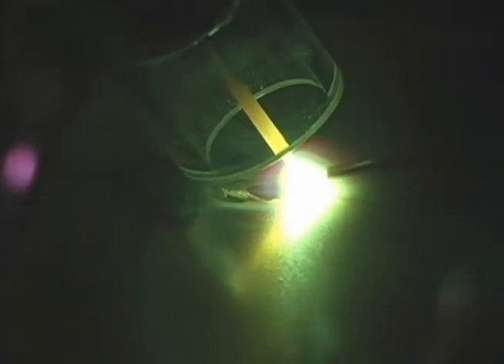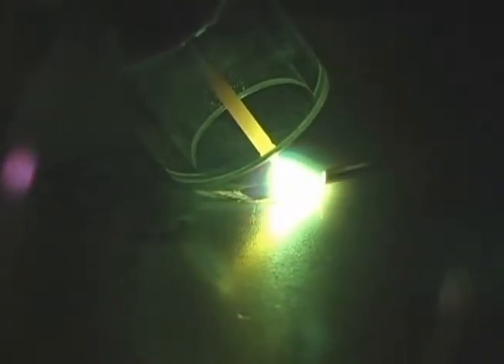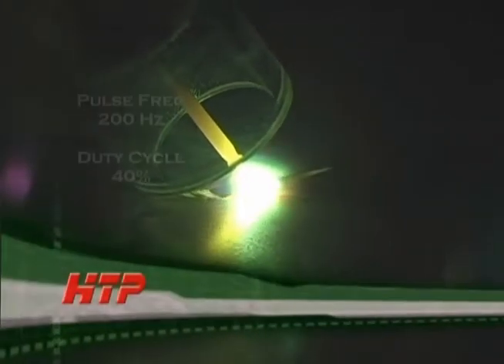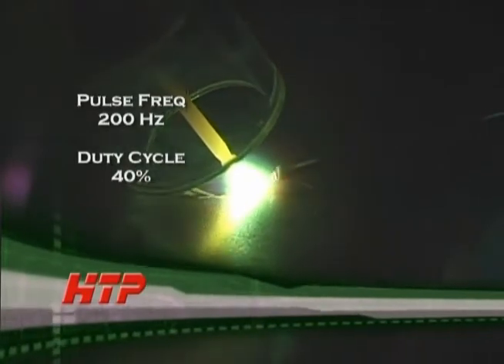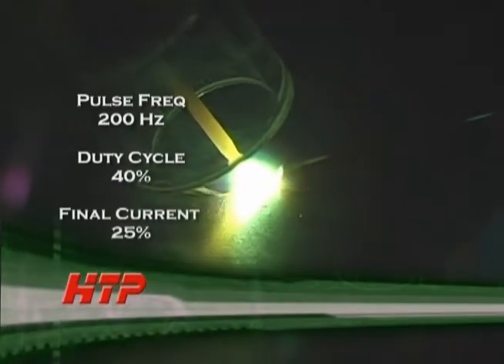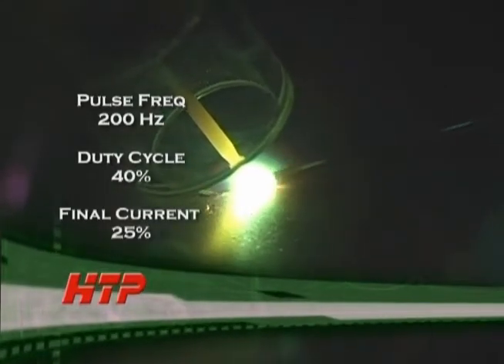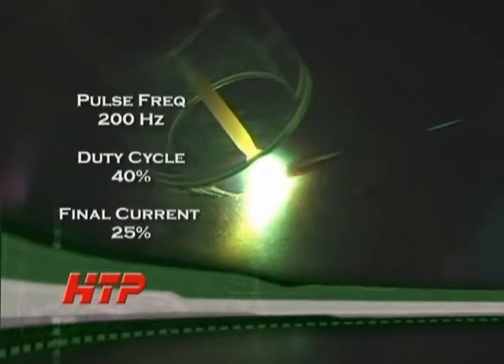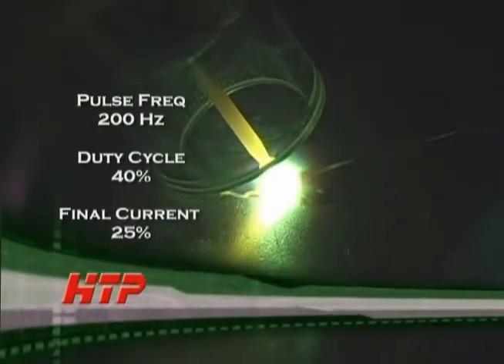In the second pulse example, we have raised the pulse frequency to 200 Hz or 200 pulses per second. You can only hear the machine pulse, not see the actual pulses since they happen so fast. The duty cycle is 40% and the final current is 25%. This really increases our travel speed, minimizes heat input while assuring penetration.